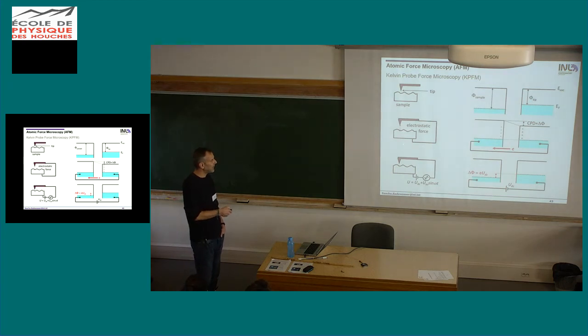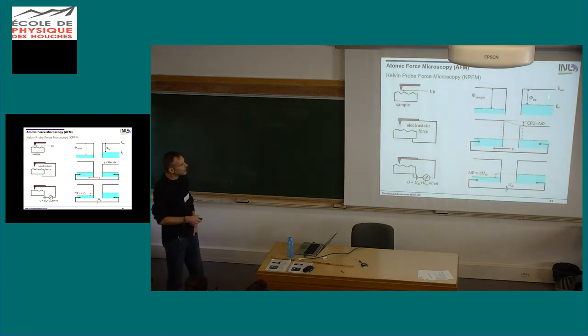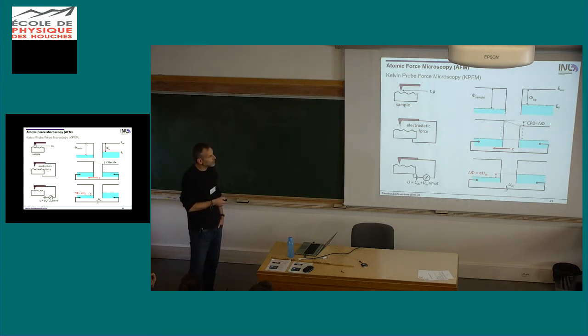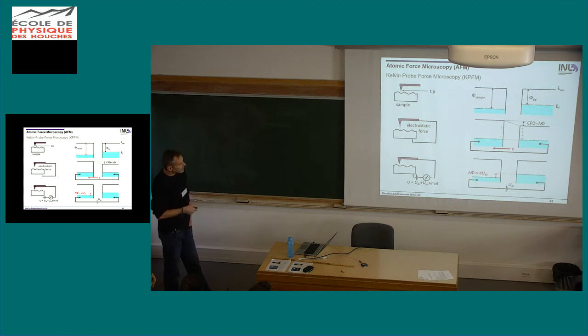Now if we take a wire and we connect the two on the back side, we will get an electron flow from the material with a lower work function to the material with a higher work function until the Fermi levels are at the same level. And at the same time, we develop a step in the local vacuum levels. And we saw a little bit of this yesterday already. So this difference here is called the contact potential difference, and this is equal to the difference in work function between the two materials. So now in Kelvin probe, what we can do is we apply a DC bias just to get the vacuum levels aligned. So one thing what I should mention here is as soon as we have a difference here in local vacuum level, we develop an electrostatic force between the tip and the sample.